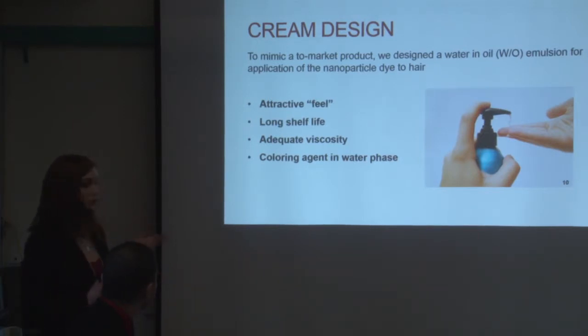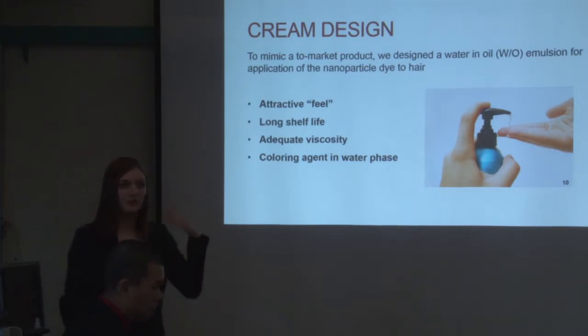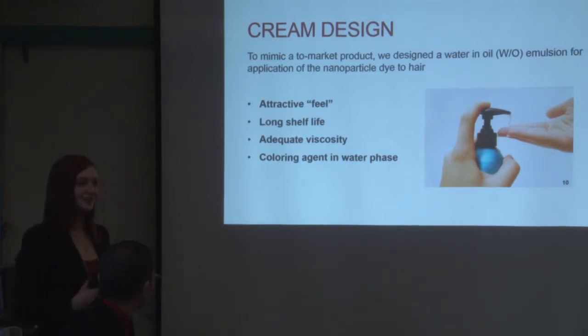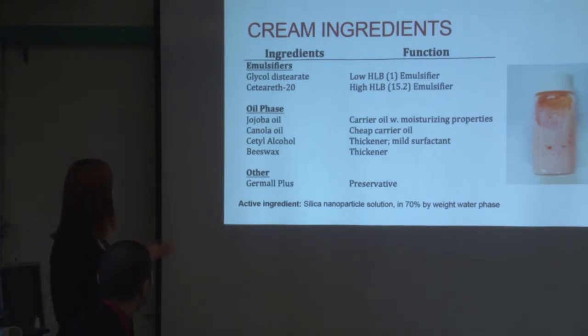So we actually used a cream that would function just like a moisturizing conditioner that you can apply to your hair, and it has to be just thick enough so it'll stay on the hair for the duration of the testing. These are the ingredients that we use, and there's a picture of the cream and the particles embedded in the cream that we've made. It's actually just an oil and water emulsion like most lotions, and it's 70% by weight water phase, and the silica particles are in the water phase. We did some testing and changing of the different ratios of things in the oil phase to try to get the consistency right.